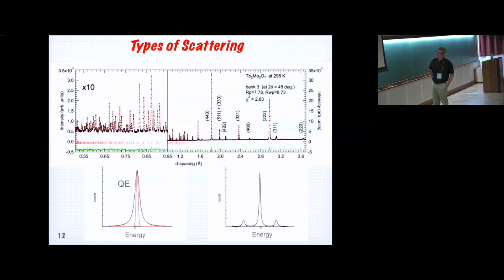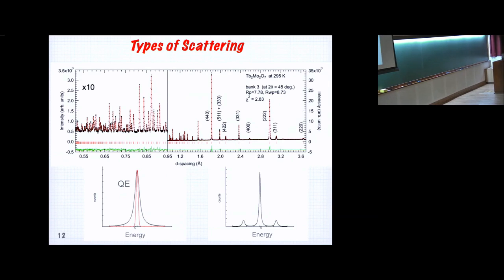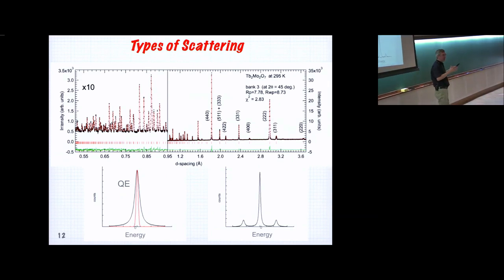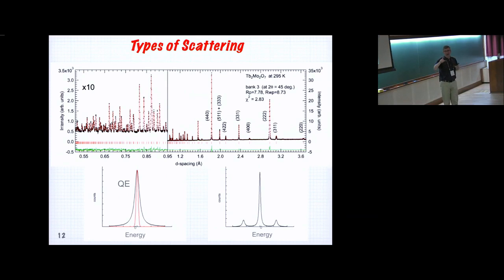It's where the instruments, if it was truly static, the instrument would give what was a red line in the middle there, a very sharp peak, but the sample put in the way broadens it. And understanding that broadening is some sort of low-lying excitation, it could be that you model it with a Gaussian in here, or it could be just a broadening of the peak. So that's, like we were saying, the lines in EPR that will broaden because of frustration in different exchanges. It could be stuff like that. And the ones where it's broadened and not a well-defined excitation is what we are more interested in.